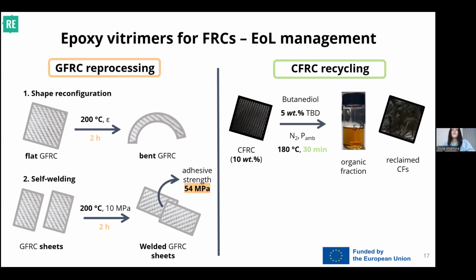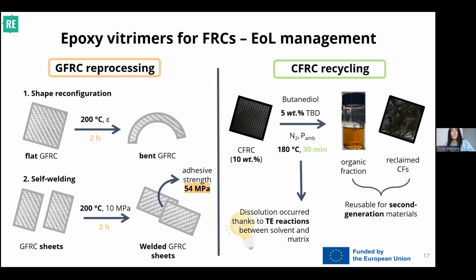As for the recycling part, we took our composite and dissolved it in butanediol, which is a diol containing OH groups, and in which TBD, so the transesterification catalyst, was also dissolved. And the complete dissolution of the matrix was obtained in 30 minutes at 180 degrees Celsius. So we were able to recover the organic fraction and the reclaimed carbon fibers that were both possibly reusable for second generation materials. You notice that in this case, we have created a sort of extrinsic vitrimer because the resin itself, so also the matrix, was vitrimeric, but we were also able to create exchanges between the resin and the solvent, thanks to the TBD dissolved in it, meaning that this way the resin was able to dissolve itself.